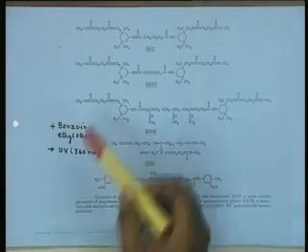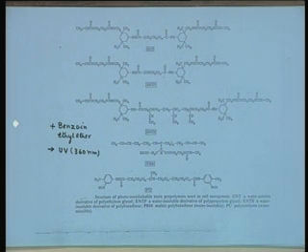These are the precursors of certain photo cross linkable polymers. That means these molecules can be polymerized using UV radiation in the presence of a photoinducer, a catalyst kind of situation, and benzoin ethyl ether is used in most cases as an inducer for photo cross linking. These materials can be dissolved along with the enzyme, and then polymerization can be started by exposing them to ultraviolet light at 360 nanometer for a few minutes. In a few minutes the reaction is over, and the gel preparation containing the enzyme molecule is made available.